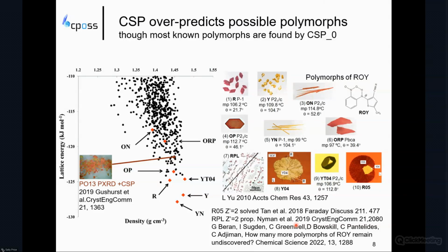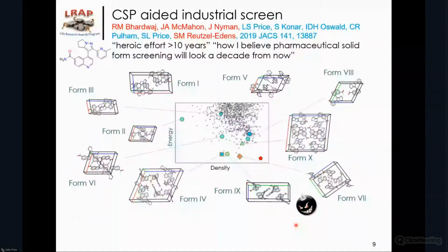Now, this might sound like this is academics working on this system. What about industry? Well, we were lucky to work with Eli Lilly on this drug molecule for the CSP, where we ended up with 10 polymorphs with characterized crystal structures. And this was a heroic effort at screening. And you can see for the CSP that there are lots of spots on there, masses of crystal structures that do not correspond to known ones, including this global minimum, which was therefore a danger sign that there was a more stable structure yet to be found.